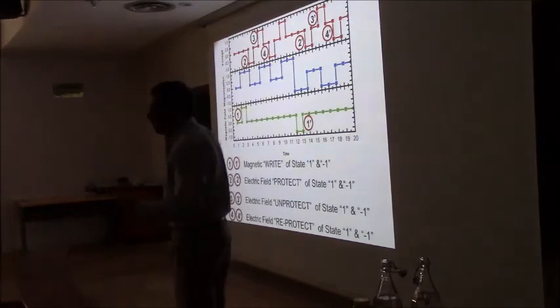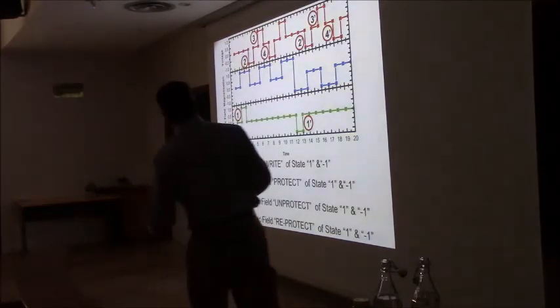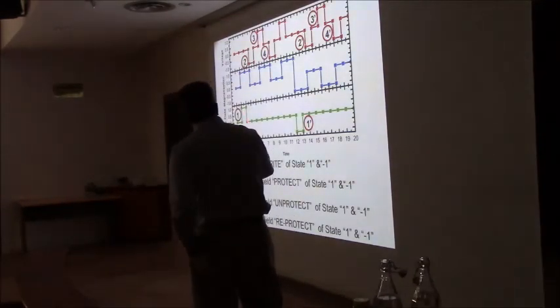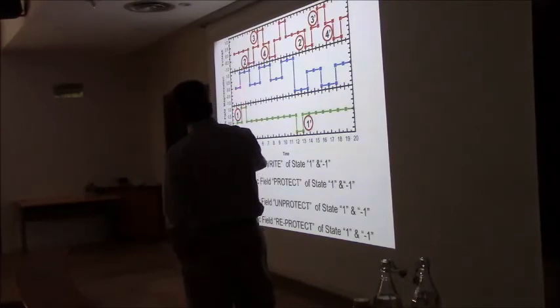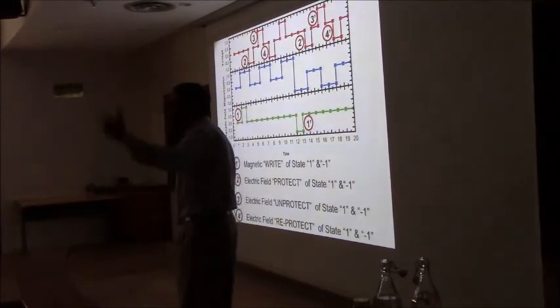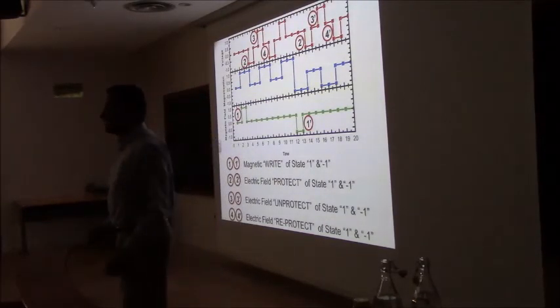So we've done a whole bunch of measurements which showed that indeed I can put it into one of these states. For example, I can magnetize the iron and put it into the one state. I can come in, and this is the magnetization response. I can come in and apply voltage. I can go back and completely hide that magnetic state.